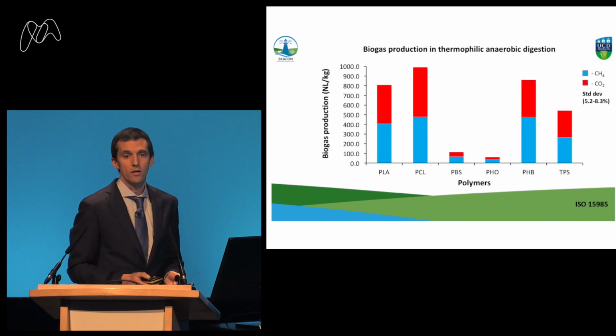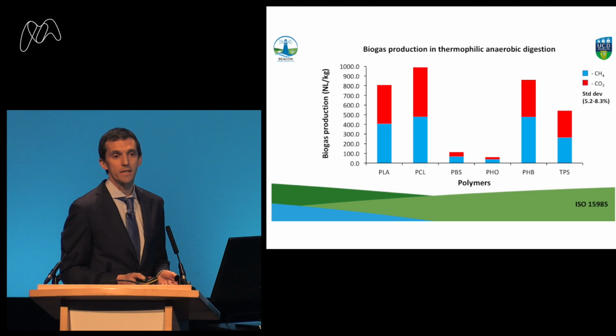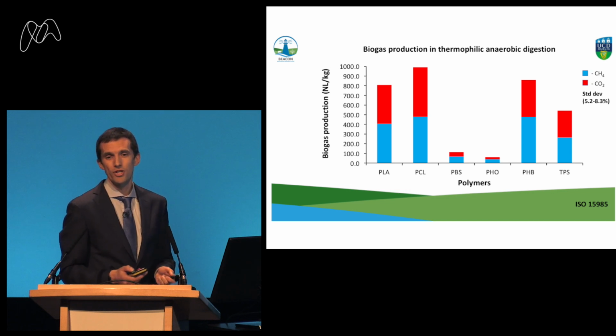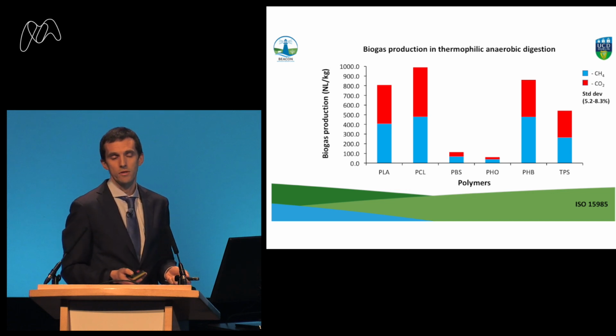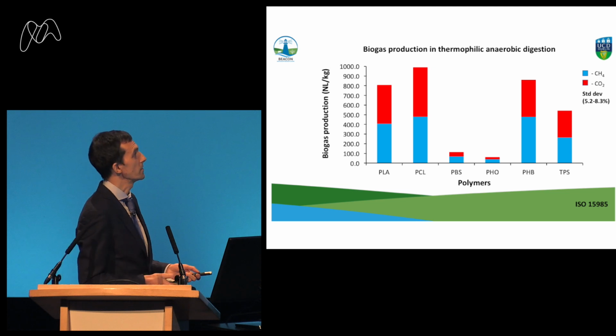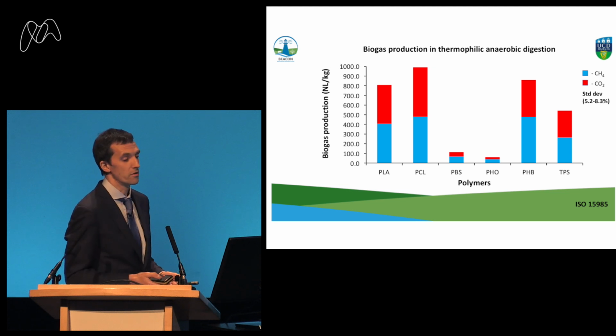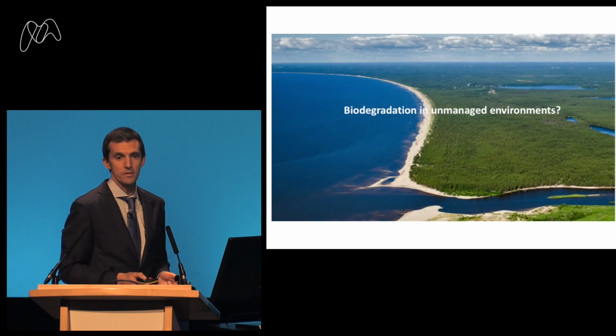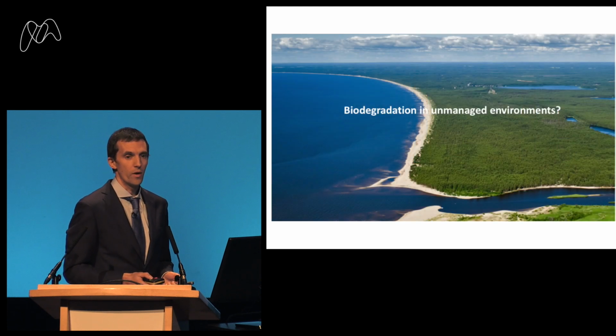And when we looked at biogas outputs, it's pretty much a 50-50 split between methane and carbon dioxide. In general, some of the best are 60-40, let's say, methane to CO2. But what we see is, in general, about a 50-50. But what about these plastics in unmanaged environments? What's actually happening when they are not managed?